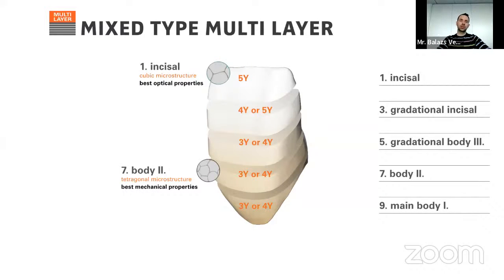I wish to mention, because this is also popular nowadays, the mixed type of multi-layer. It means that at the incisal edge you have a translucent material, for example a 5 yttrium type of material, which is really translucent and really aesthetic, but in the body area you have a stronger, more opaque material. It's a nice idea, a good idea from the industry. Actually, we don't have these kinds of products, because we analyzed our competitors and we see that this solution of mixing different kinds of materials is still not reliable.